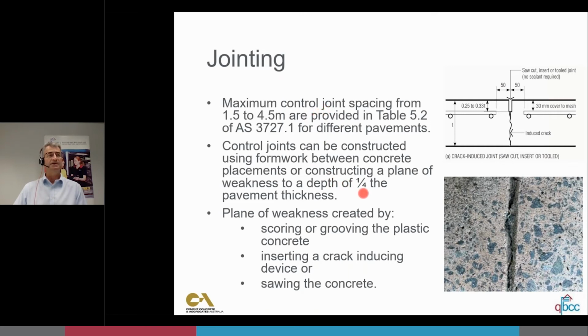A note here that it should be to a depth of at least 1/4 of the concrete to ensure that that's where the crack does initiate. And then the weakness planes, as they're called, can be done by scoring or grooving the plastic concrete, inserting a crack-inducing device, and sawing the concrete. When it comes to sawing the concrete, you kind of need to get on it pretty quick. So ideally the same day, or as early as possible the next day. You've probably got a bit more time in the winter than you might have in the summer. But if you don't get in there early enough with the saw cuts, you might find that the cracks have appeared where they want to.